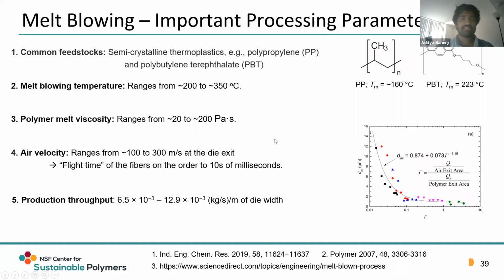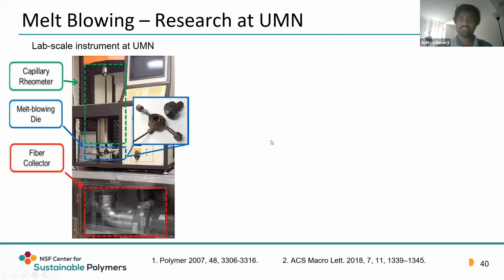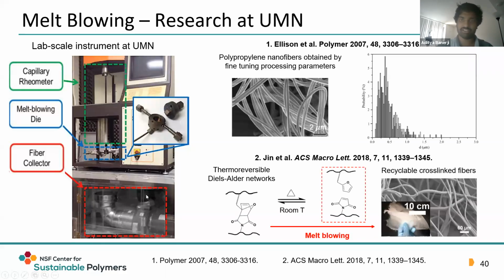Moving to the next slide, this is the equipment we have at UMN in Amundson Hall, where a capillary rheometer is attached to a melt blowing die, shown in the blue inset. The capillary rheometer pushes the polymer melt through the melt blowing die, which then gets drawn down into small, thin fibers that are collected in the bottom section.